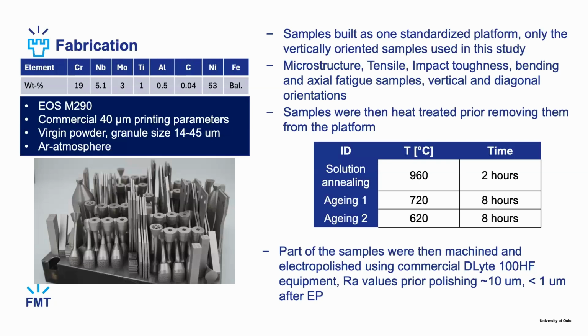After the printing, the samples went through conventional solution annealing first at 960 degrees for 2 hours, and then double aging for 8 hours, first at 720 and then at 620 degrees. After removing the samples from the platform, part of the samples we electropolished using commercial DLyte 100HF equipment, and we could decrease the surface roughness value from 10 microns to less than 1 micron. So we could really test the effect of the material itself and not just the surface.